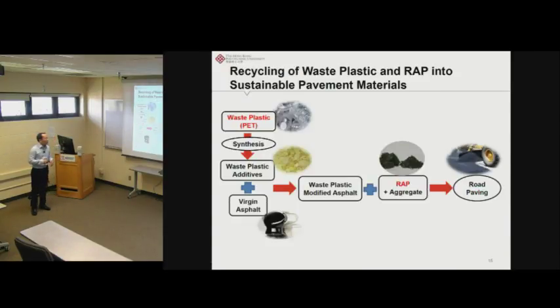So here is what we propose to do. First of all, we are going to collect the waste plastic. As I mentioned, right now we are mainly working on waste PET, which is the plastic used to make water bottles. Then we are going to chemically treat the waste plastic and convert it into some additives, which we call waste plastic additives. Then we add this additive into the virgin binder to produce the waste plastic modified asphalt or binder. Then we mix it with RAP and virgin aggregate to make the bituminous mixture which can be used for road paving.